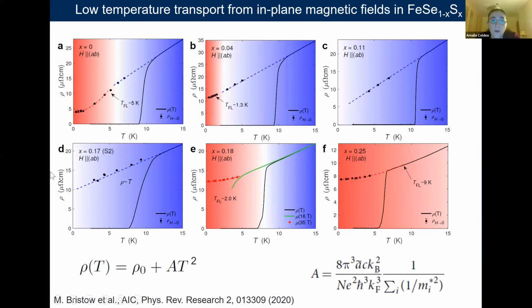We have data all the way to 0.3 Kelvin. These are difficult experiments, to get all the way to low temperature and suppress the magnetoresistance. You have to do longitudinal magnetoresistance studies in about 45 Tesla or higher. But I can give you another example. Look at the 4%. This is very deep inside the nematic phase. If you look at this data, you will say, well, this is linear in T. But we see very beautiful quantum oscillations, and if you zoom in within this regime, eventually it is T-squared dependent. I understand.